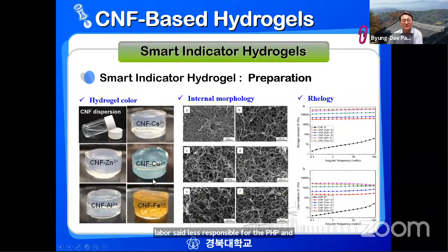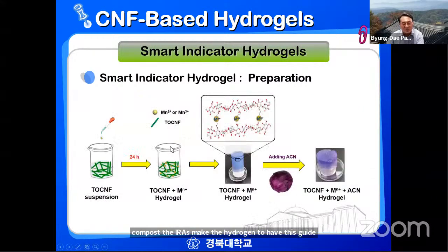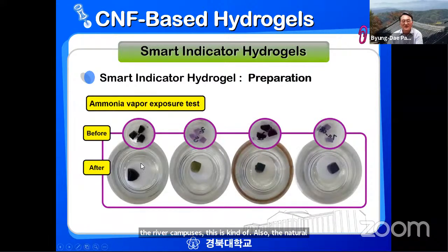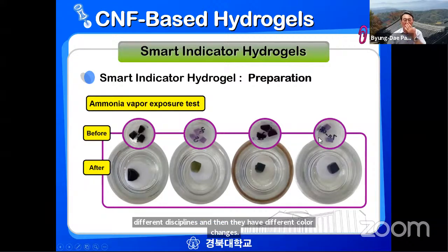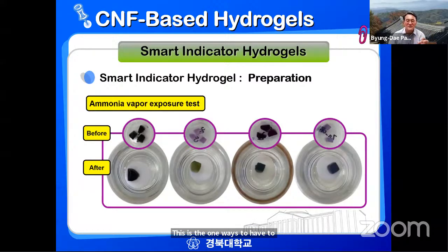And also we try to use different cations, coppers, the irons, to make the hydrogels. And then this time what I'm going to do is we have cations and then TEMPO CNF, and then we add the anthocyanin from the red cabbages. This is kind of also the natural dye, to detect color changes. You know, we prepare the hydrogels with anthocyanin, and then we expose to ammonia vapor gas, and then check any color changes, this kind of different cations, and then they have different color changes. So this is one way of detecting color change of hydrogels as kind of smart or functional hydrogels, detecting color change in the food or any materials.